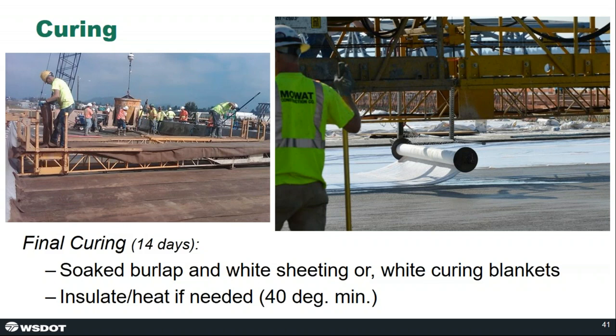And we do set a 40 degree minimum temperature for the concrete during these 14 days. We want the contractor to keep the temperature above that minimum. If they go below it, they lose credit for a day of cure and have to extend the cure. And that's a good incentive for the contractor to promote good practices, but ultimately it's hard to make up for a day of curing early on in hydration by extending the cure longer.